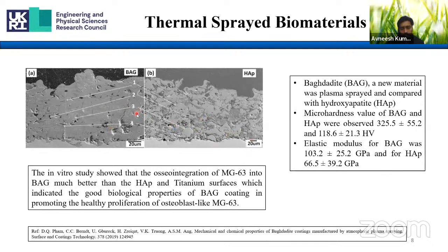Then he discussed in his talk that the micro hardness value of these coatings was far better than the hydroxyapatite coating, which we can see here. For bagdadite, it was around 325 HV, and for hydroxyapatite, it was around 118 HV. Similarly, for elastic modulus also, bagdadite had 103 gigapascal, and hydroxyapatite was around 66 gigapascal. So from here, we can say the mechanical properties of bagdadite were far better than the hydroxyapatite coatings.